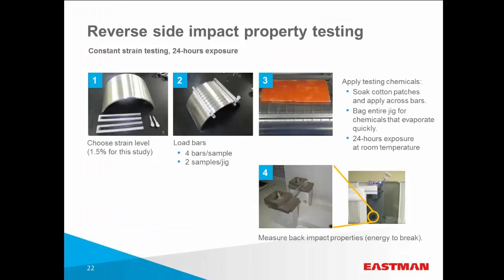So here's how we measure our chemical resistance or chemical compatibility. We take a strain gauge, we place molded plastic samples on there, we put a patch on there and soak the patch with the disinfectant. We allow it to sit for 24 hours at room temperature, and then we do a backside impact test to measure if it became ductile or brittle based on any kind of environmental stress cracking that may have occurred. Next slide.